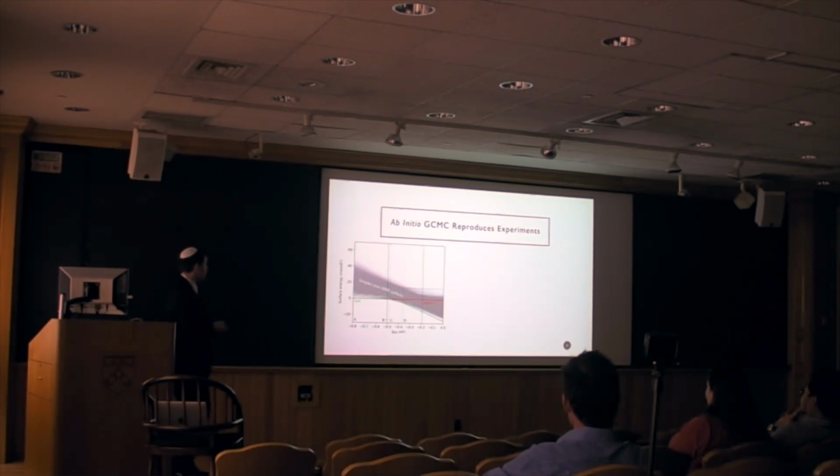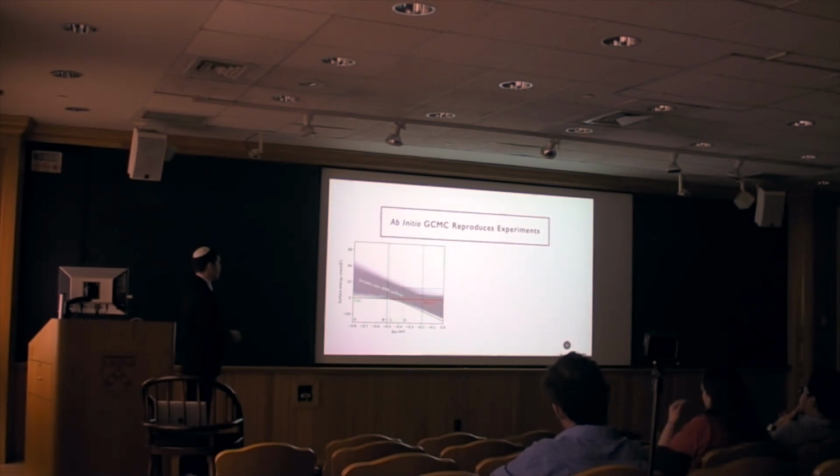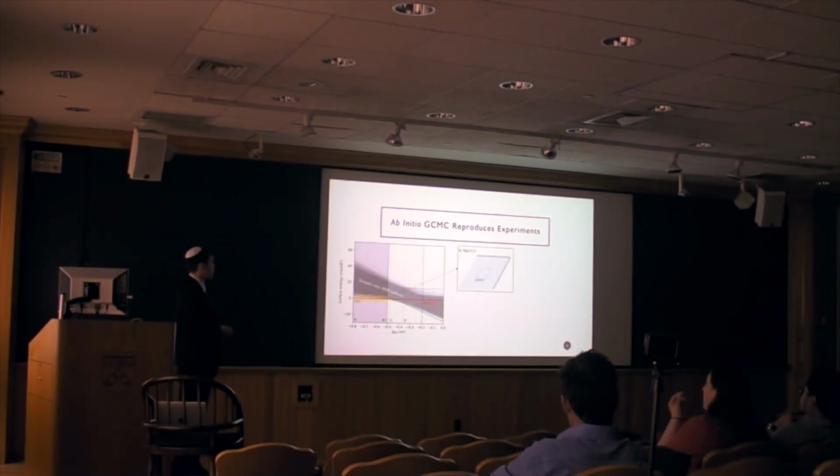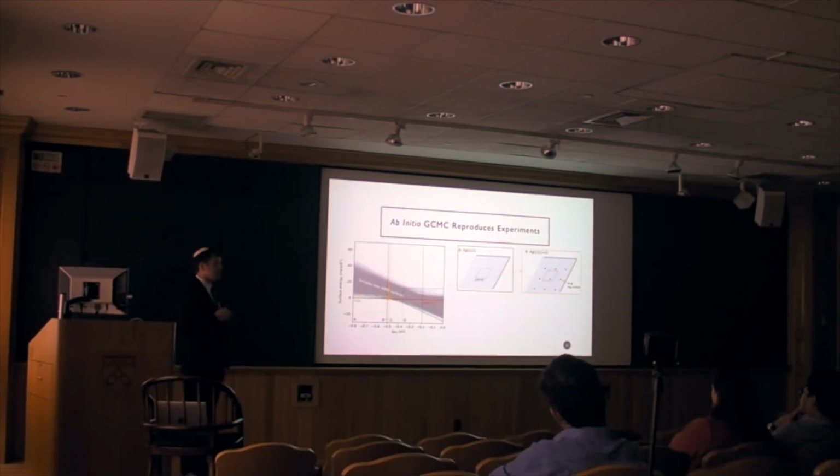And just to note, in this region right here, we have a negative chemical potential. This means oxygen is very low oxygen pressure. There's not much of it around. And here it's very high oxygen pressure. So in this first regime of low oxygen pressure, we get what we'd expect. It's a bare silver 111 surface. However, as we increase the pressure of oxygen, we find that oxygen adsorbs atomically on the surface.